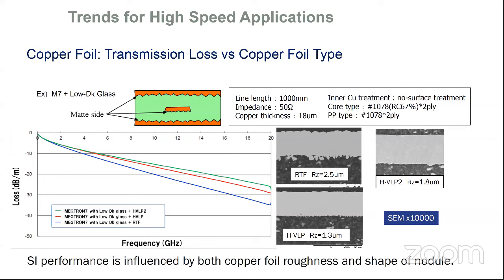Well, we're still on the topic of copper foil, but it is important. This particular test vehicle, we're using our ultra low loss material, MEGTRON7, plus the low Dk glass. We're keeping the resin and the glass constant for this test. As you can see, the TV is made up with half-ounce copper, 1078 prepreg in the core, as well as the bonding ply. For the purpose of this particular experiment, the copper trace or circuitry has no surface treatment. We wanted to remove any element or contribution from a copper surface treatment. You can get away with this in a lab making test vehicles, but you can't get away with it in real life, not running a treatment, if you will.